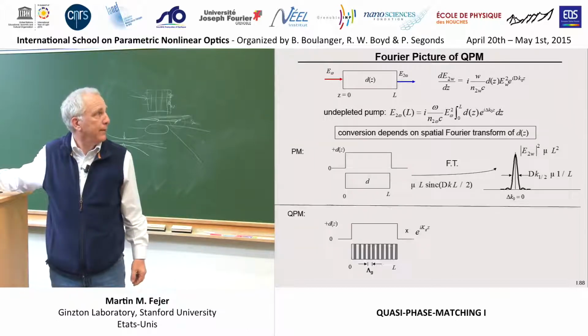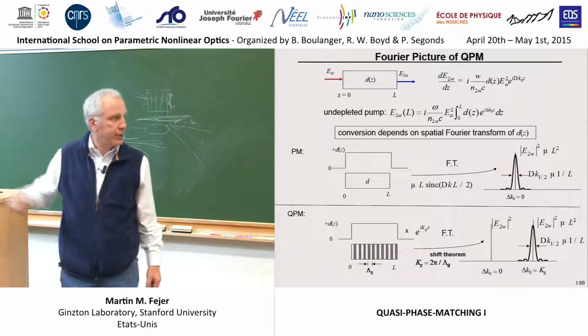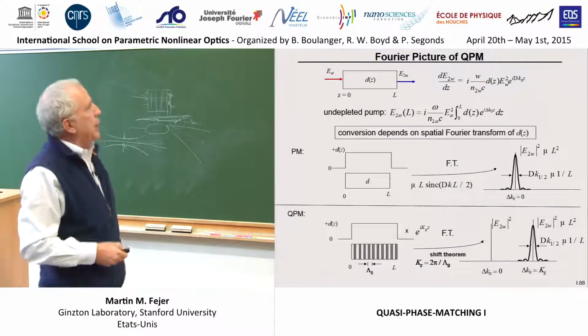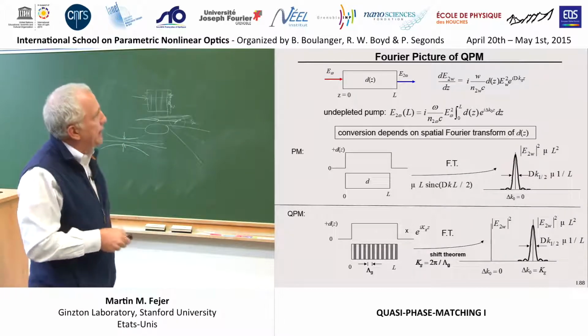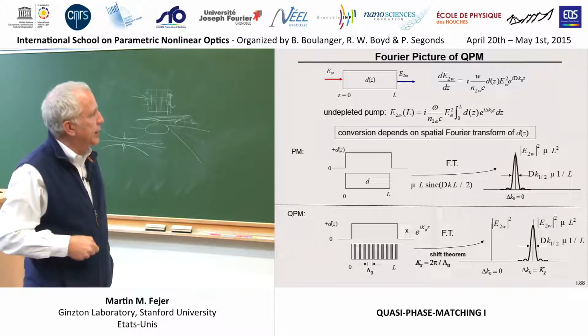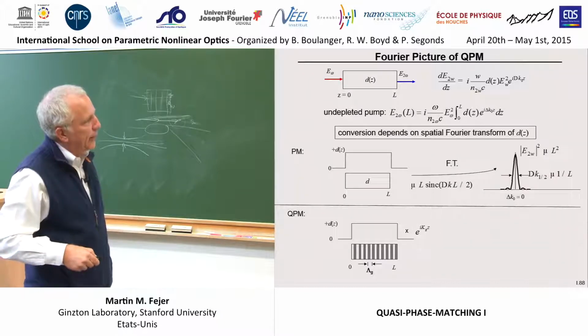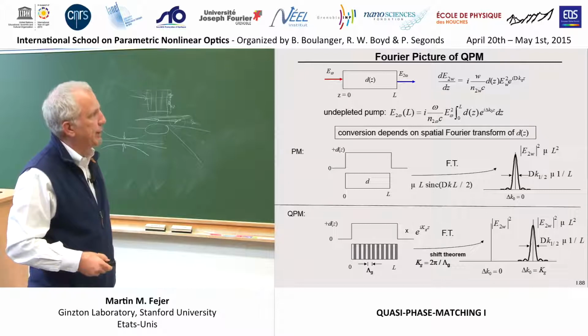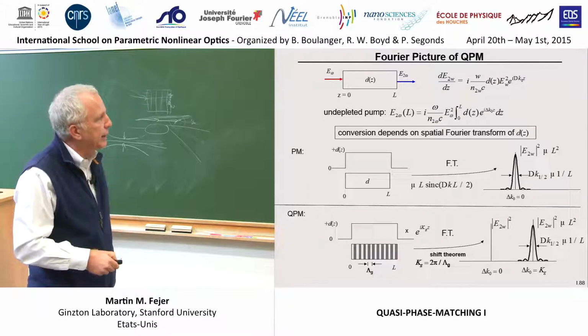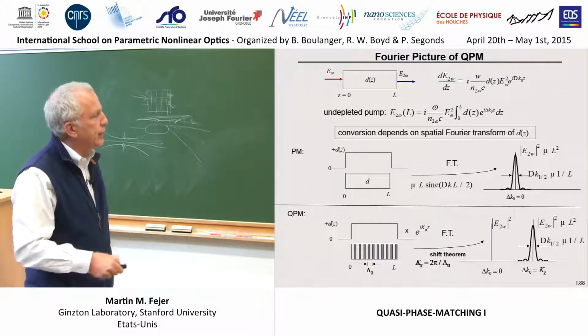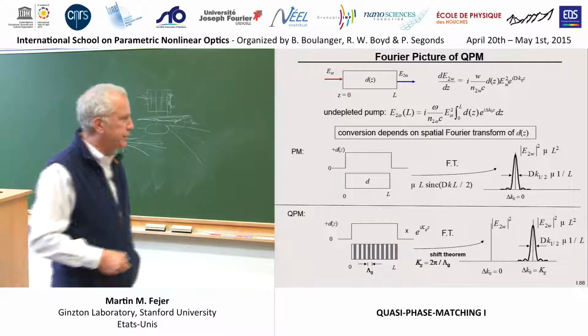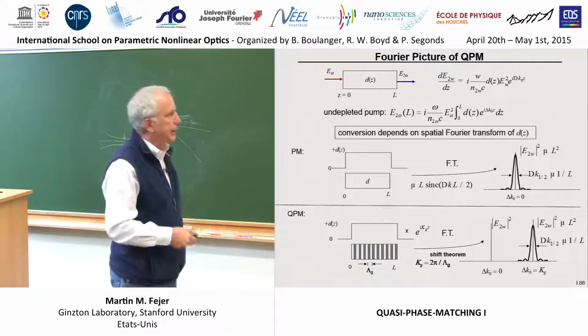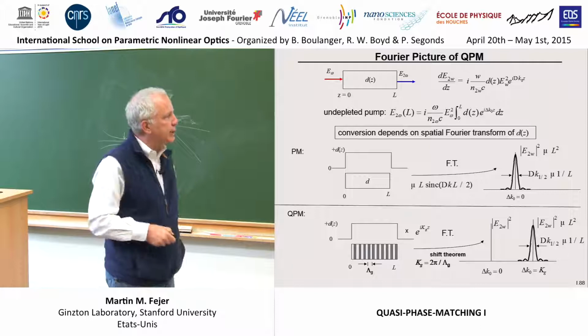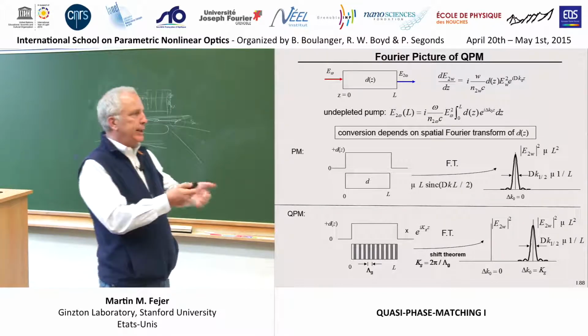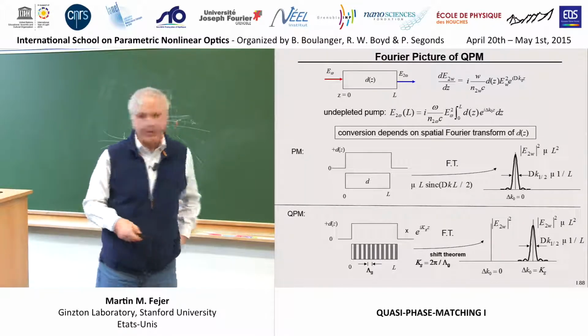We said already that the tuning behavior of this thing, the phase matching, the efficiency of the mixing for second harmonic, will be centered around delta, the K grating equaling the phase mismatch, and we'll have a width that goes inversely with the length, et cetera.